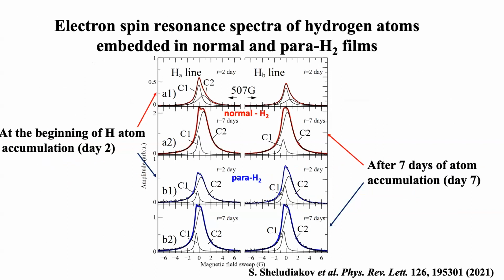The red curve is the result for normal hydrogen, where 25% is para and 75% is ortho molecule. The blue curve is the result for para hydrogen, where there is no ortho molecule at all. The results are shown after 2 days and after 7 days of accumulation.